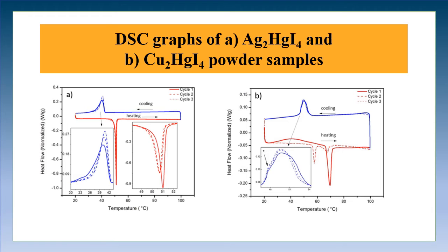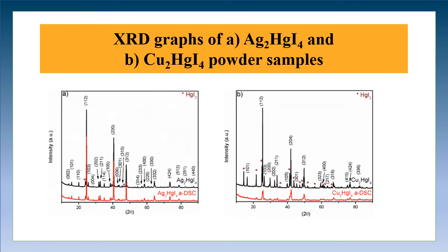A very different behavior is observed in copper tetraiodomercurate. In the first cycle, the minimum was observed at 69.6 degrees Celsius, which is reversible with hysteresis at 49.70 degrees Celsius. A small shoulder is also observed around 47.8 degrees Celsius. While in the second and third cycles, the peak when heating is at 75.8 and 75.5 degrees Celsius, which is reversible with one peak around 49.7 degrees Celsius. This figure shows the XRD of the powders.